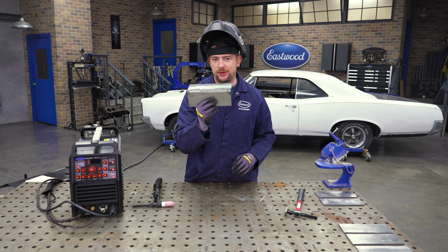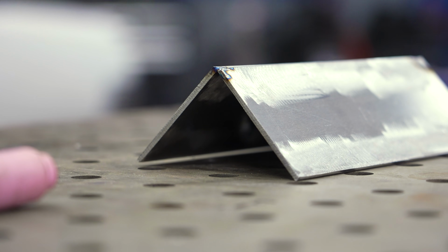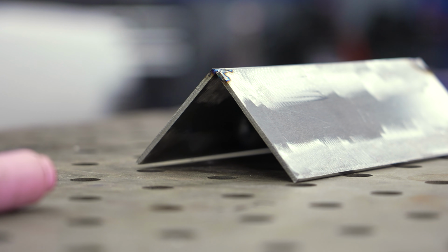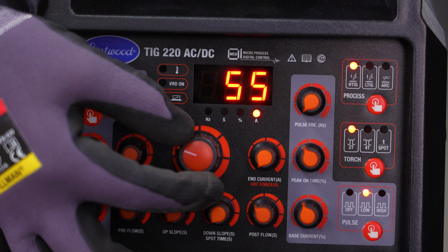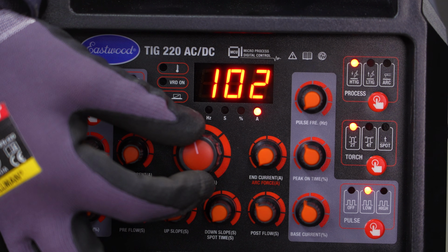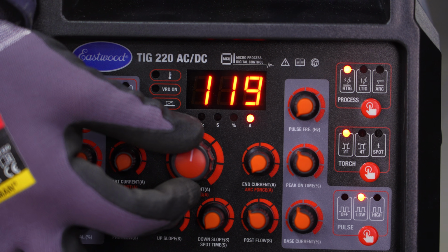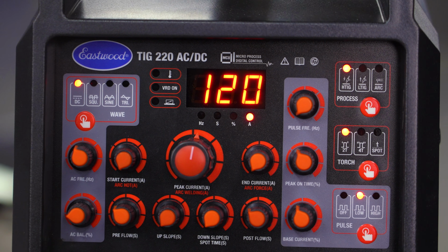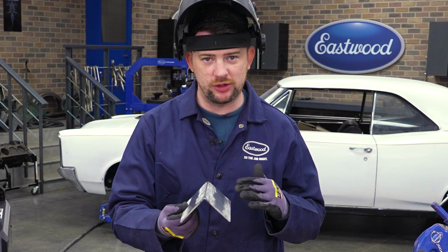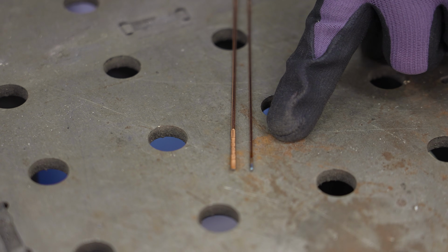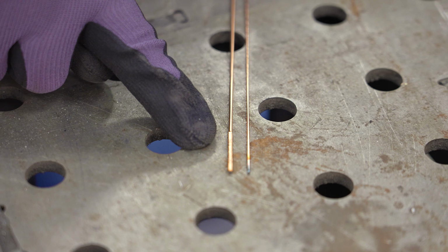Now we're gonna step up to a thicker material. This is gonna be like a 90-degree butt joint, and I'm gonna weld it with the slower low pulse, which is gonna be a 0.5 hertz again. We're gonna do 40% and 40%, but this time I'm gonna ramp the amperage up to about 120, and we should get pretty good penetration. I'm also gonna step up from my 045 filler rod to a 1/16 inch filler rod.